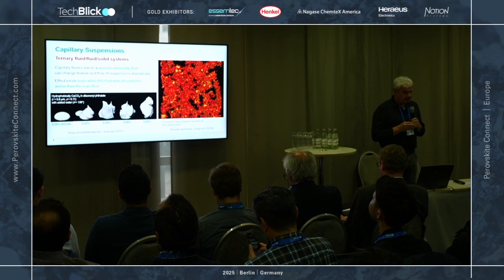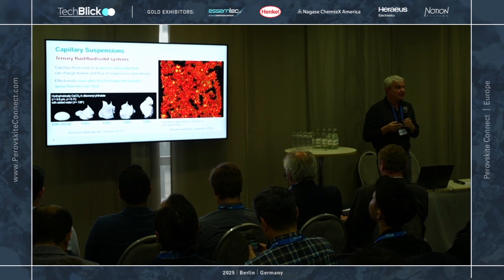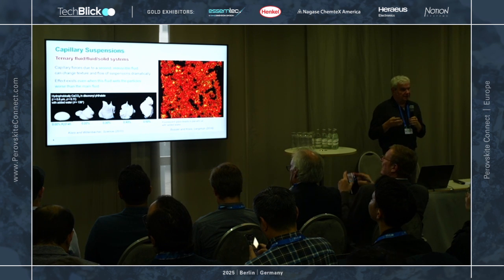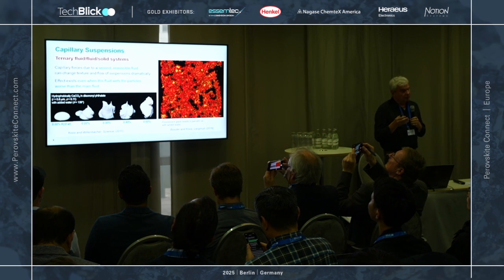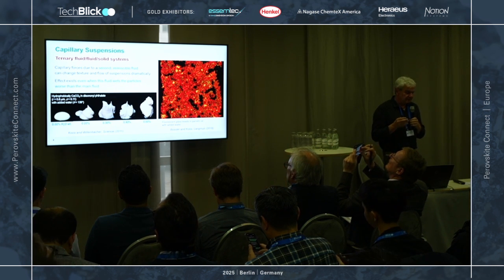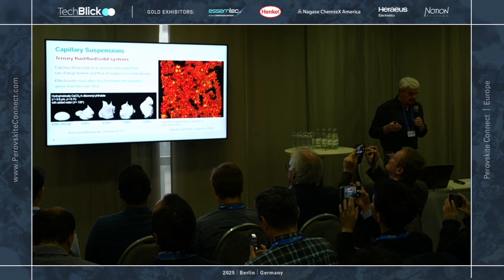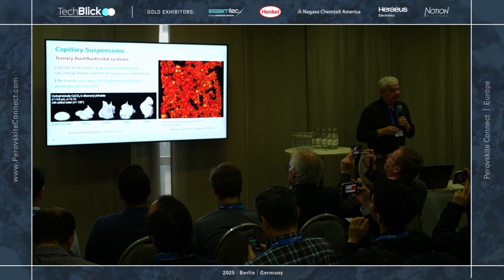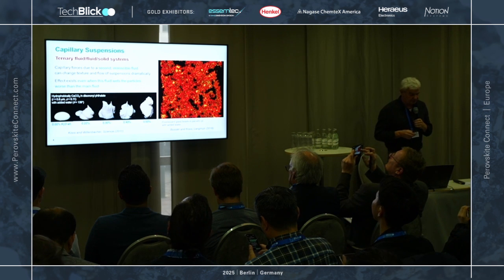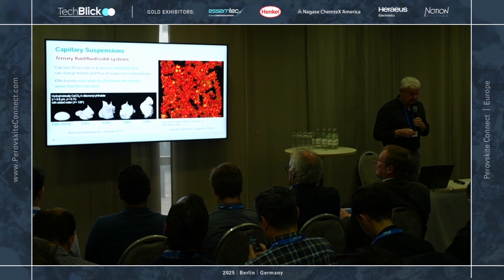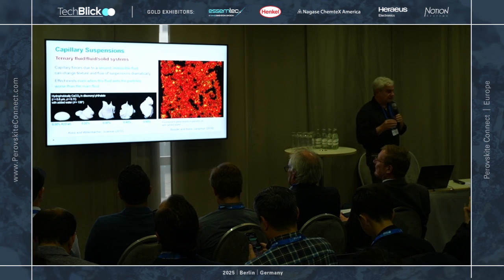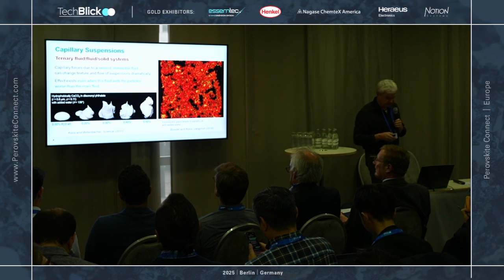They are ternary fluid-solid systems. Usually particles can be suspended in a liquid or in a polymer, when you talk about a polymer composite, and such a binary system may have low viscosity at low filler content. And then you add trace amounts of a secondary fluid. In this example, you see how a suspension of calcium carbonate in an organic solvent transitions from a milk-like texture to a cheese or cream-like texture just by adding trace amounts of a secondary fluid, which is water in this case.